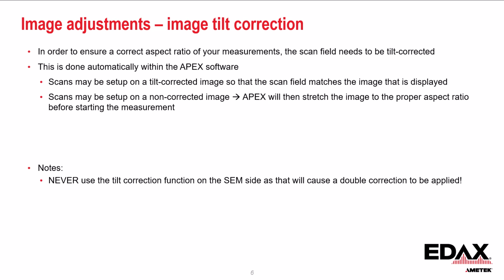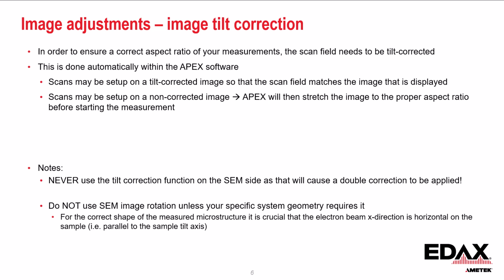Now, something important you have to remember is that you should not use the tilt correction function on the microscope, because Apex doesn't know when that has been switched on, and it will do it again. So when you switch on the tilt correction on the microscope, you will get a double correction applied, and the aspect ratio in your image will be wrong. Also, do not use the image rotation function on the microscope unless your system geometry specifically requires that. Because if you rotate a little bit and the horizontal direction of your SEM image is not parallel to the tilt axis on your sample, so that the electrons go obliquely over your sample, then everything will be distorted very badly.